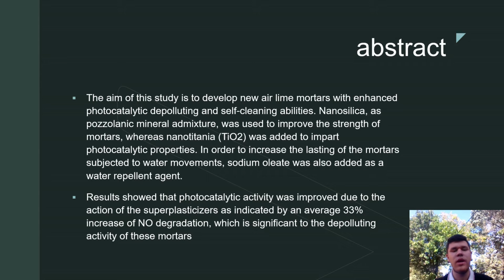The results showed that photocatalytic activity was improved due to the action of the superplasticizers, indicated by an average 33% increase of NO degradation, which is significant to the depolluting activity of these mortars.